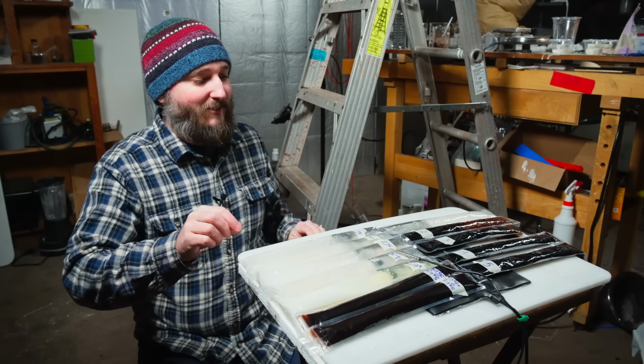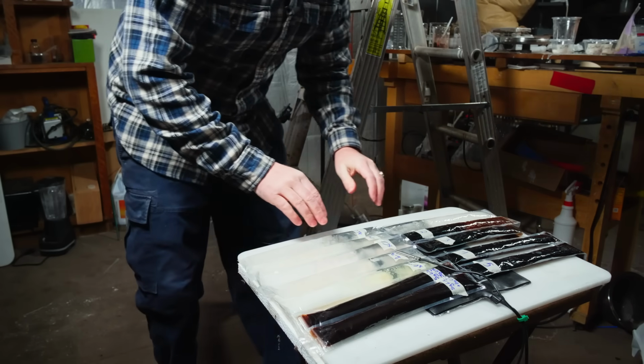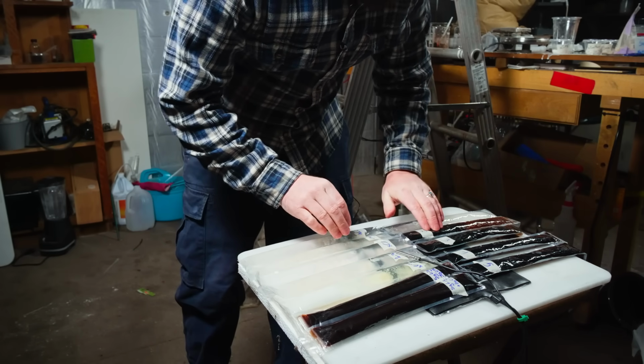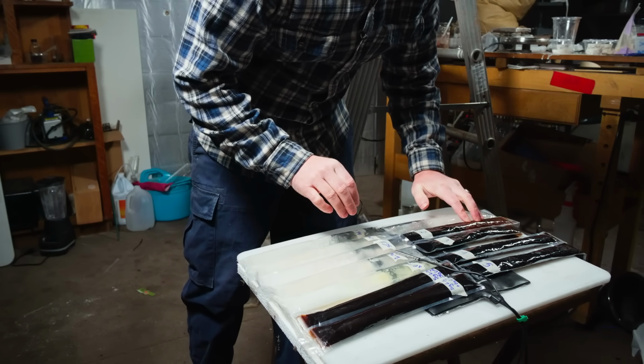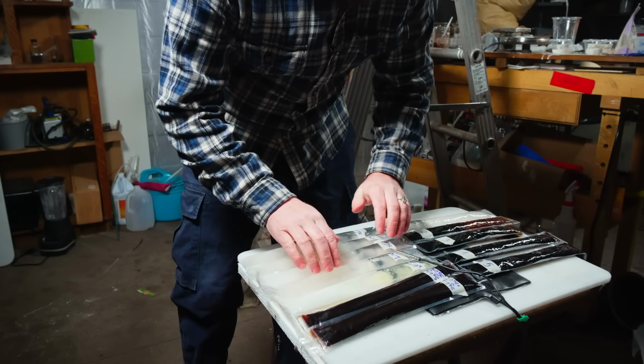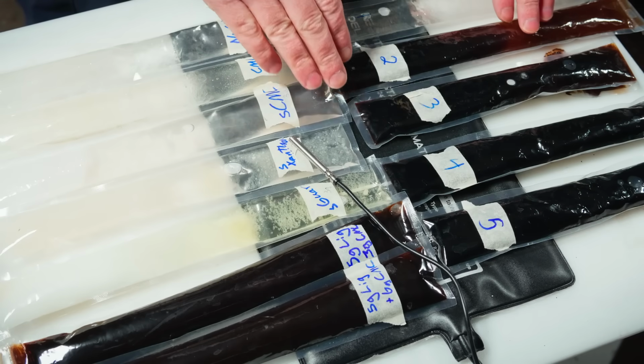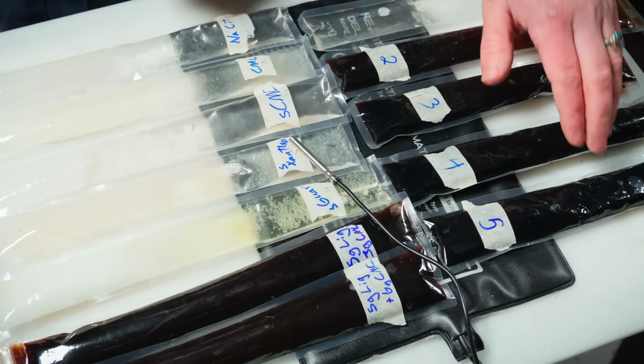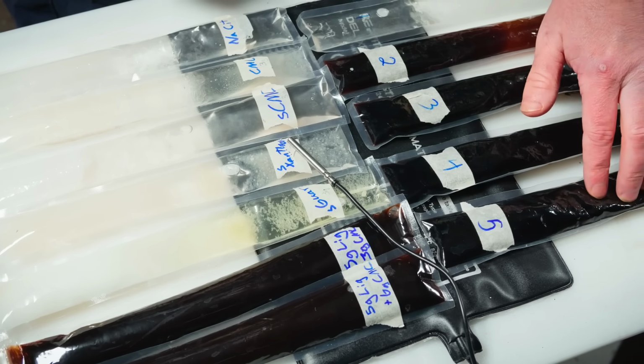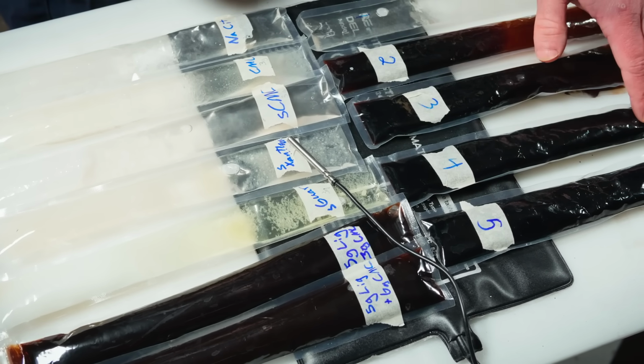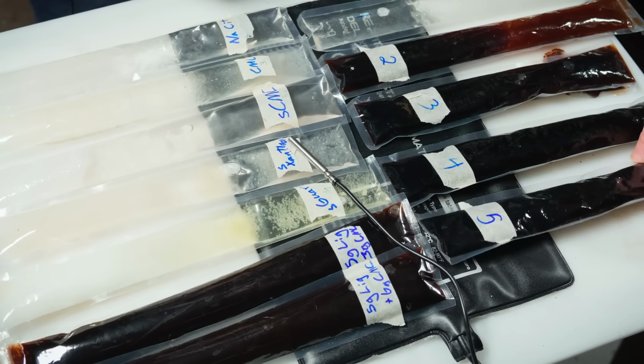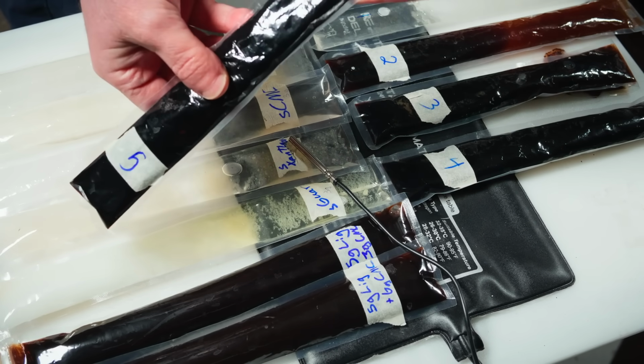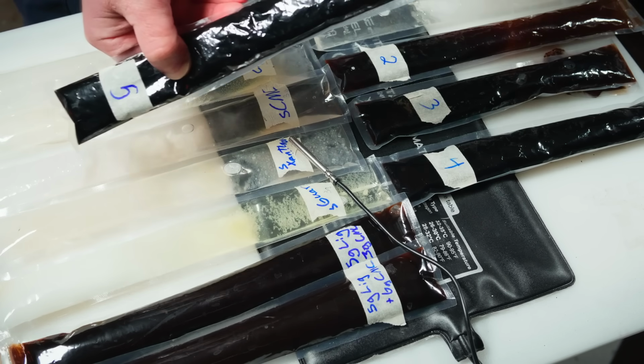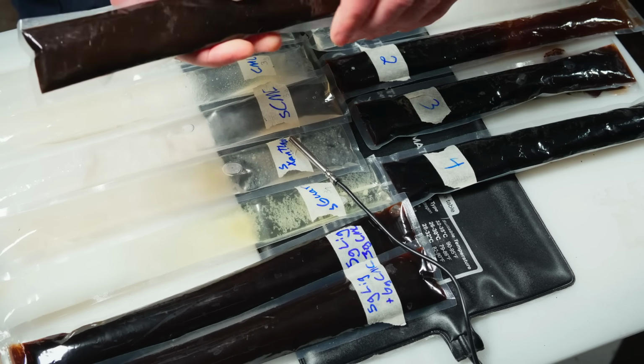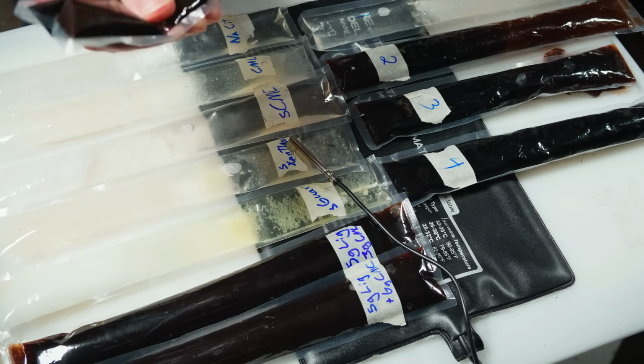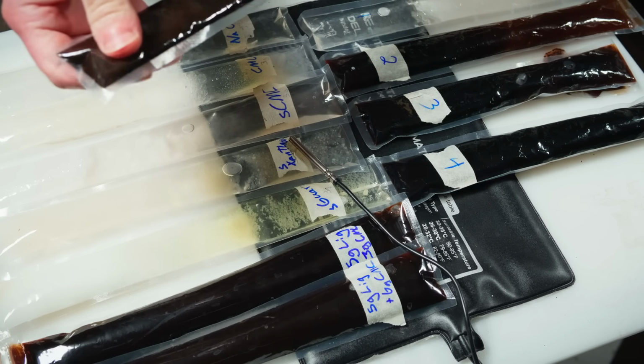What I want to do is just take a look at what are the top performers in this test. We won't look at all of these in detail because some of them were obviously pretty much failures, and others seem to have done quite well. So starting with the lignosulfonate tests, 3 through 5 performed about the same as in the vertical cool down tests. They never actually fully froze. You can see that there's bubbles moving around on this side of the sample, and there's very hard crystal structures inside. Not a great result.